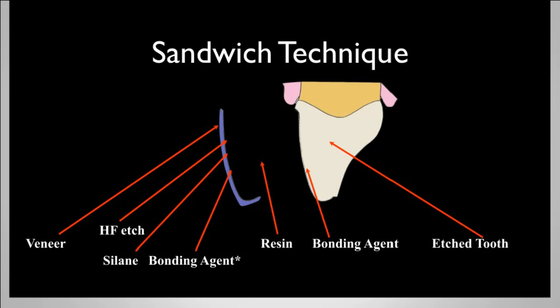When we think about resin bonding, we should think of it from the standpoint that there are two substrates. One substrate is the ceramic, the other substrate is the tooth. I still believe that whenever enamel is present, I'm going to etch it. So the more enamel quantity I have, I like to use a total etch technique. I might use a universal bonding agent, but I use a total etch technique. Whenever dentin is present, I use more of a selective etch technique, so I etch the enamel but not the dentin. On the ceramic side, whenever I have a glass-based ceramic, I use a hydrofluoric acid etch as well as silane. Whenever it's zirconia, hydrofluoric acid etch and silane do absolutely nothing, so they're not useful.